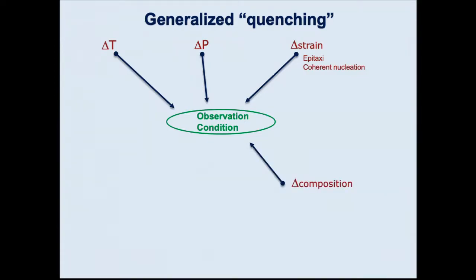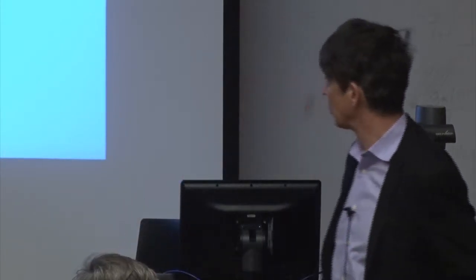We know that you can create phases at a different composition and then change the composition but retain the crystal structure. That's what is called soft chemistry, or chimie douce in French, right? You make a crystal structure, you can change, for example, some ions, diffuse them in and out, but you retain the network. And then obviously you can play with size. You can make phases that are stable at the small size, but then as you grow them, you retain them. And anatase is a great example of that, right? Anatase form of TiO2 is stabilized by surface energy. So at the small particle size, it actually is the ground state, but you can grow it to quite large particle size and not go to the ground state being rutile.